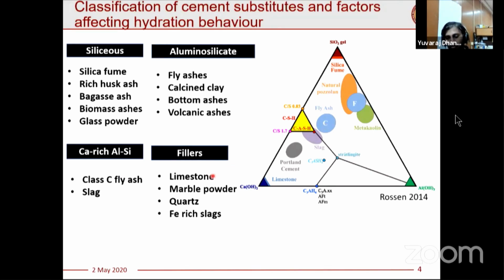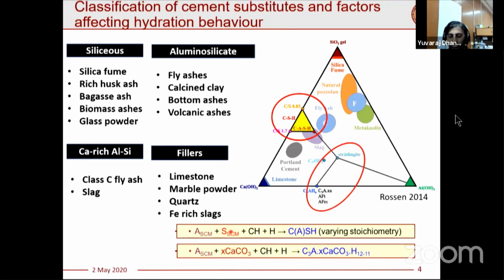And as cement substitutes, more and more increasingly, we want to use all the possible options in terms of inert fillers as well. So there are fillers like limestone, marble powders, quartz, even fine iron-rich slag, which are not so inert, can find a place in lower grade cement, like a 33 grade cement, as inert fillers in it. Essentially, in this raw material chart, the basic reactions that are meant to happen are between the alumina and silica in the SCMs along with calcium hydroxide, which produce hydration products in this region. And then there are other reactions which are possible especially because of the alumina in the SCM with components such as calcite to produce hydration products in this zone. So we have a very confined zone where raw materials are available and hydration products are going to be formed.